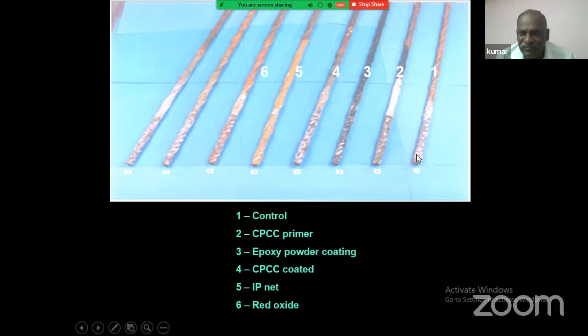You can just see here the surface. Uncoated steel, I mean concrete, it is already on adhesion, higher adhesion, and there is passivation happening. When you are coming to primer, it will be a little less. When you are coming to epoxy, the adhesion of the concrete is almost nil. It looks as fresh. This is actually taken out from the concrete. And when you are coming to CPCC, almost the surface is like the uncoated steel. Because of that, you are able to get very high bond strength.